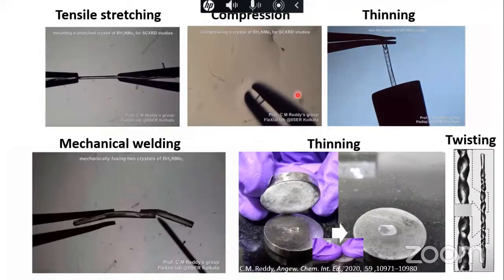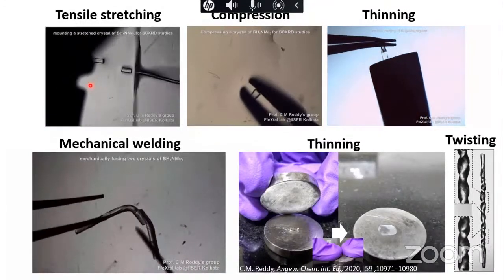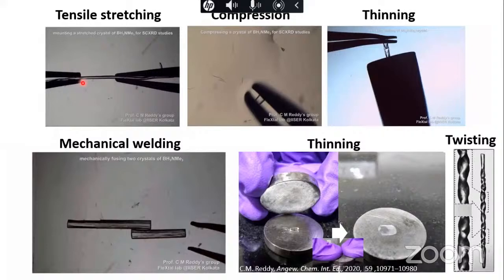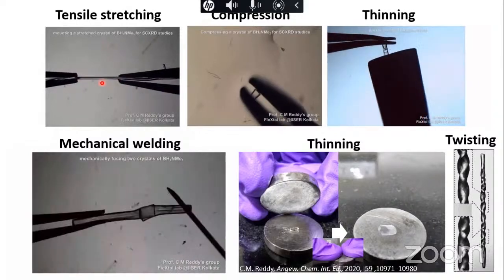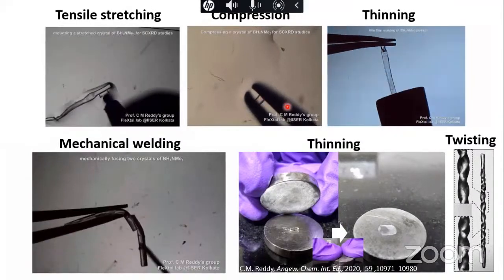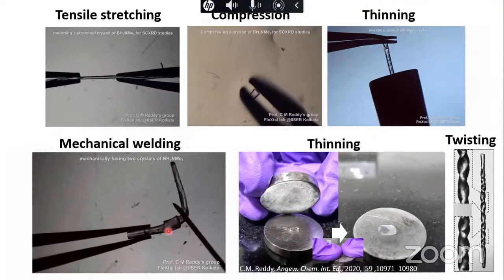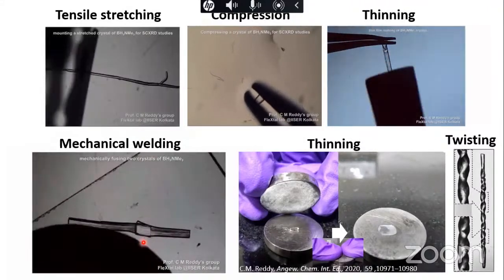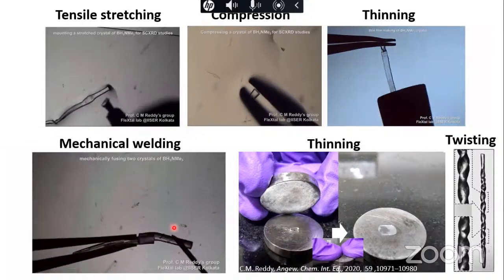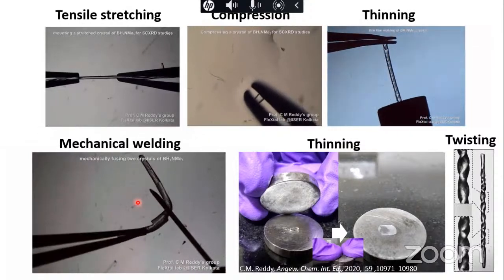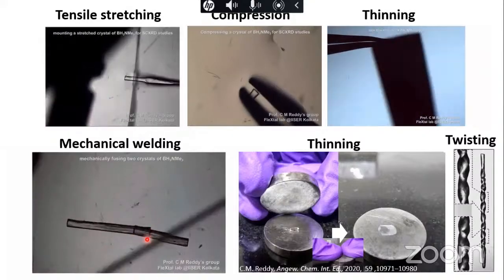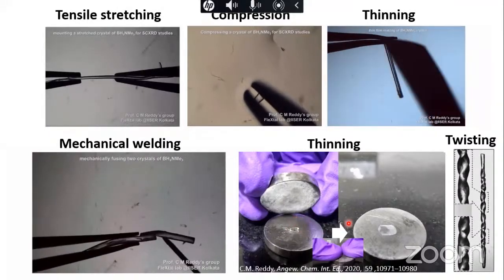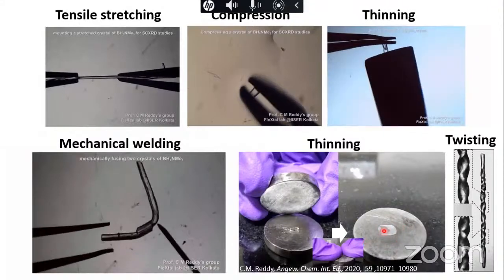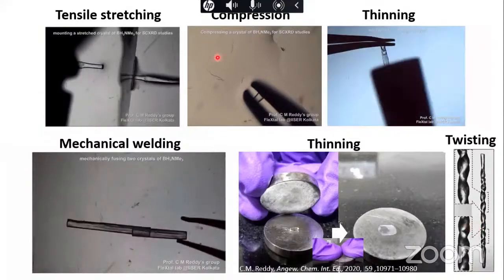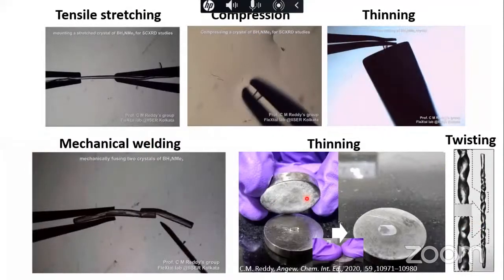So these soft crystals, the first 2, form very soft crystals, and you can pull them. And this is very unusual for molecular crystals. You can pull them, you can compress them, you can thin them, and you can also put 2 crystals together and compress them. Then you can stick them to each other. This is almost like welding. And you can also take them and compress them, so you form a thin film. You can even rotate them, twist them, and go on doing a lot of things with these crystals, almost like copper at high temperature.